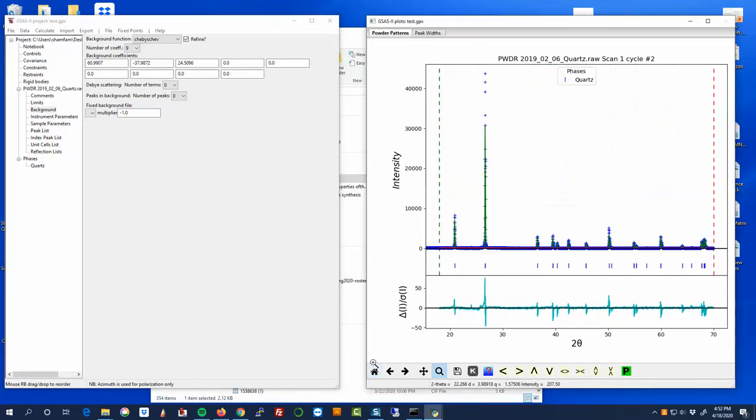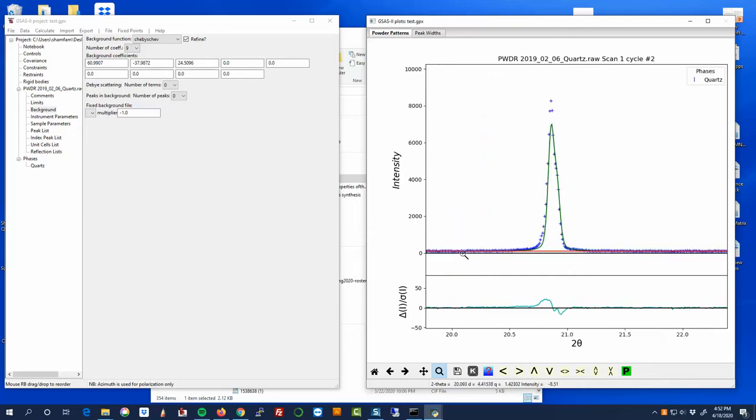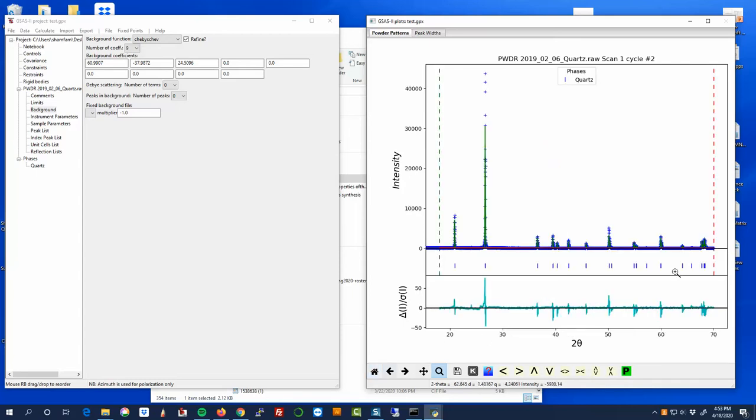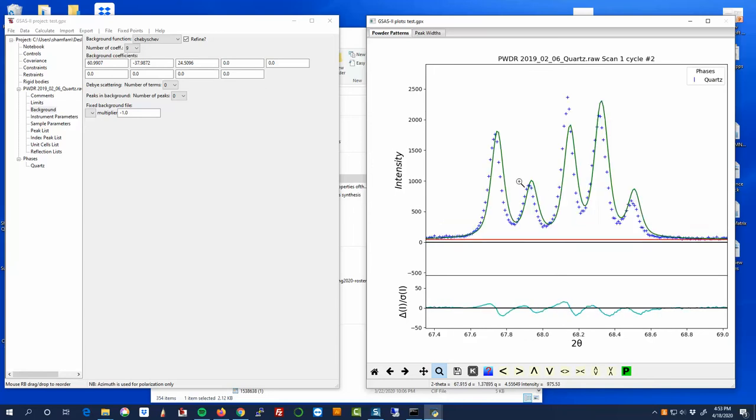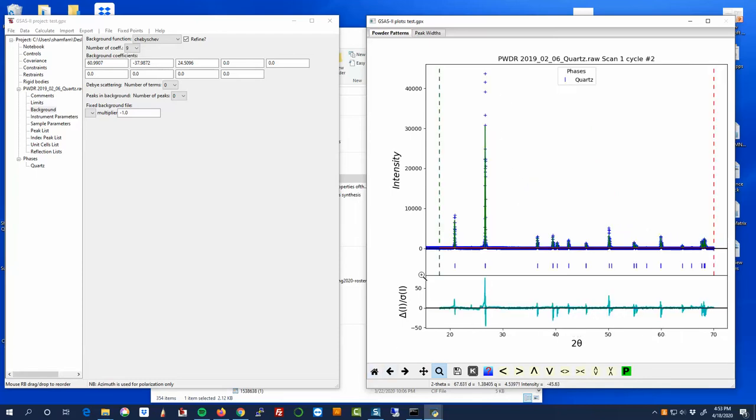So the general principle in refinement is that you always want to identify which things are the furthest off and work on refining them first. And how you do that is you zoom in and you look at your peaks. And I can already see that my position of peaks is not quite right. So I see data that's to the left of the peak here. And my data points are to the left again of the model curve. I also see this sort of up and down signal from the fit. If I zoom out and I come and look at high angle peaks, it's even more obvious. So in all these cases, it looks like that blue observed peak is to the left of where the model is putting it. And so that tells me that something is off with the peak position. Remember, these little blue hyphens here are what is designating the position of the particular peaks.